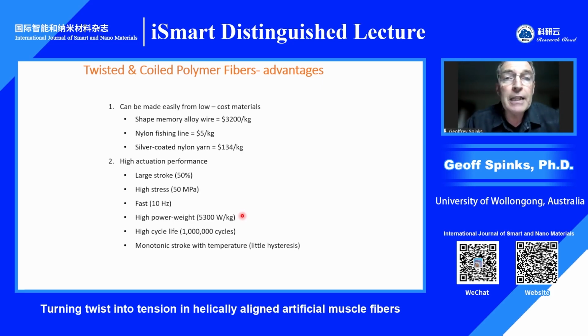If you remember way back at the beginning when we had the chart of different power to weight ratios of engines and motors and so on, anything up to 1,000 watts per kilogram was actually right up the top there. So these systems are very powerful, and of course they're tiny. In terms of mass, they're just a few grams. So they're occupying that space in that chart of power to weight versus weight that really didn't exist before. And also they've been shown to operate over many millions of cycles without any degradation. And they're monotonic with temperature for those thermally actuated systems. And if it's done slow enough, there's very little hysteresis.